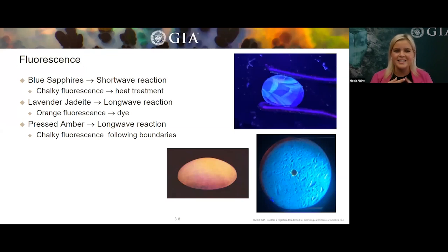Lavender jadeite, if it's dyed, some dye will fluoresce an orange to long wave reaction. So again, not all dye, but some dye do. Pressed amber reacts to long wave and it creates this chalky fluorescence, and then it kind of follows the boundaries of all those pieces of amber that were pressed together, and you can see that in the bottom right.